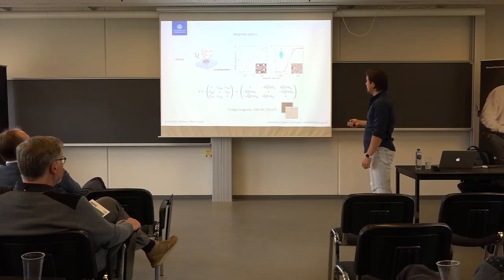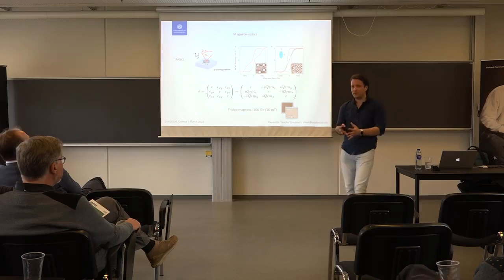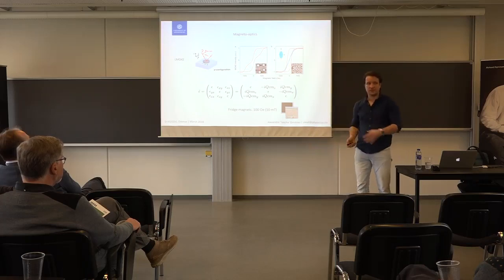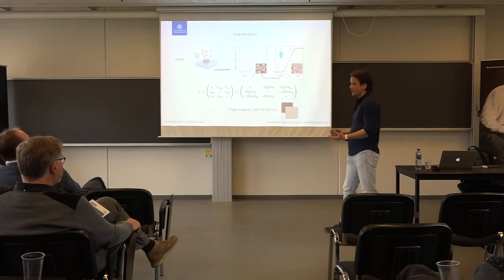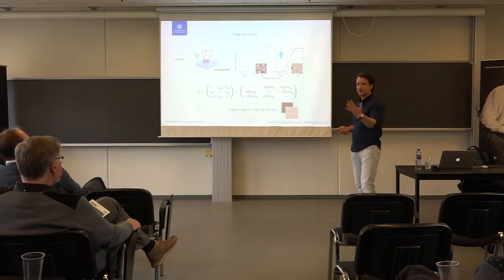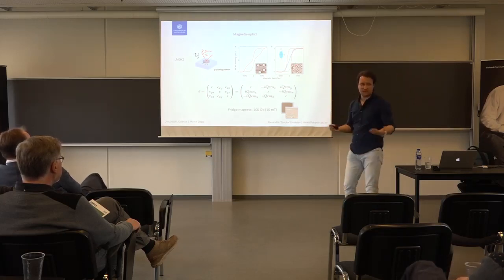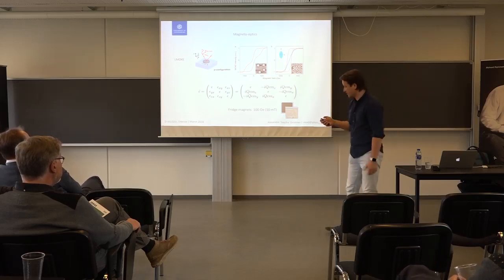And so you see actually here for the disks, you reach the saturation at much higher magnetic fields, but just because you helped the magnetic field a little bit with the shape of your nanostructures, you can saturate them at much lower fields, and potentially that is good for your magnetic memory. This is a short intro into how magneto-optics really serves humanity to measure the magnetization of your structures and eventually the function of your hard drive.